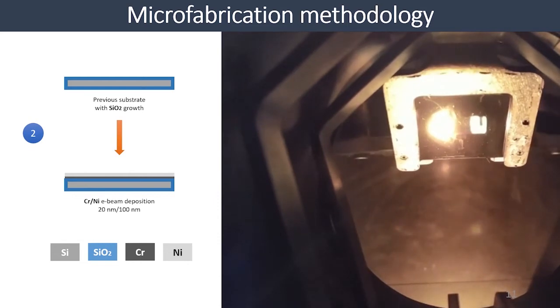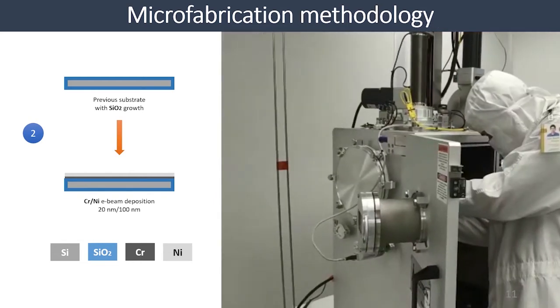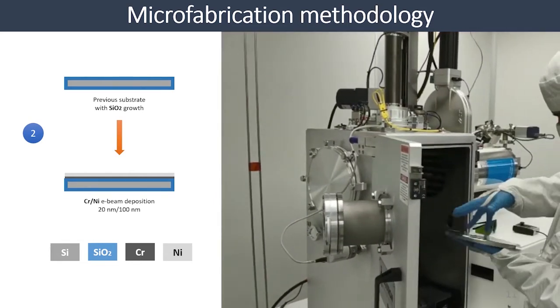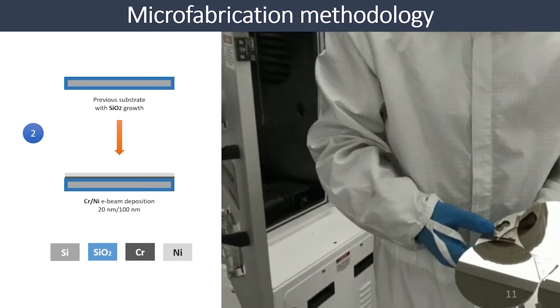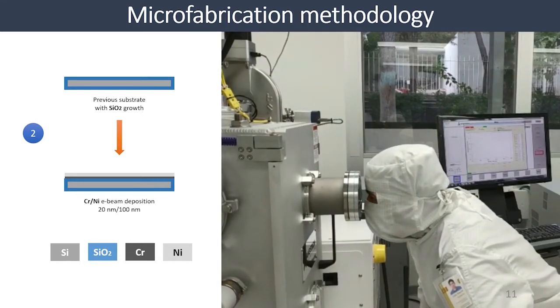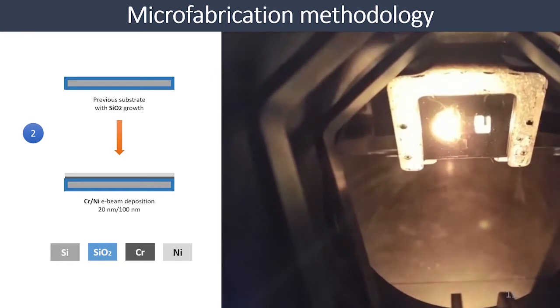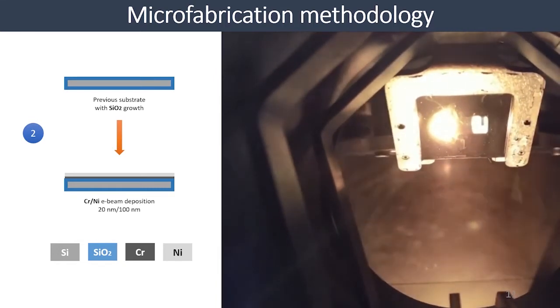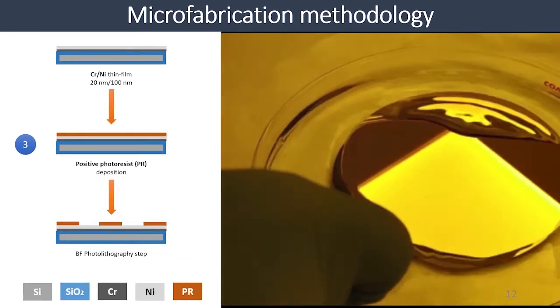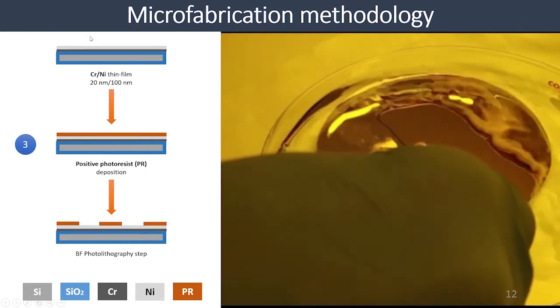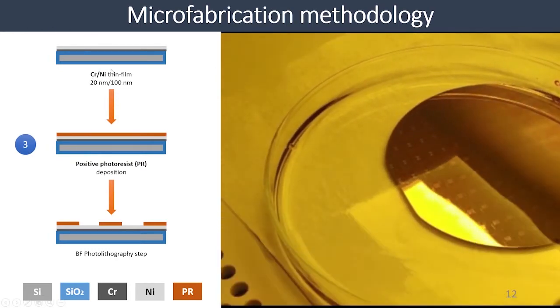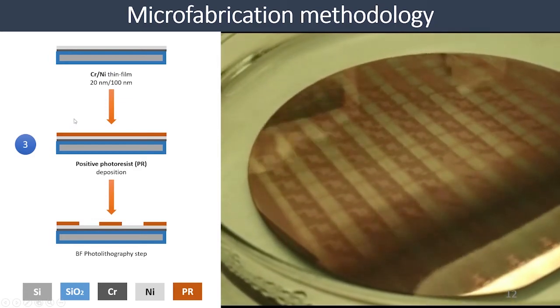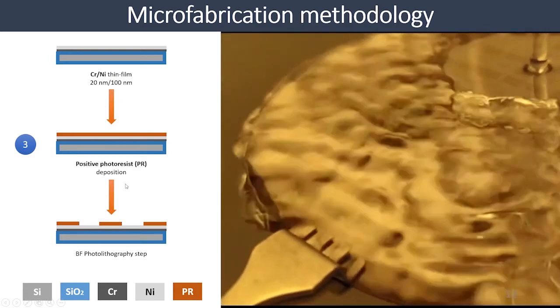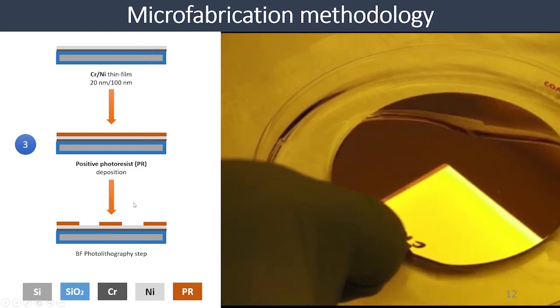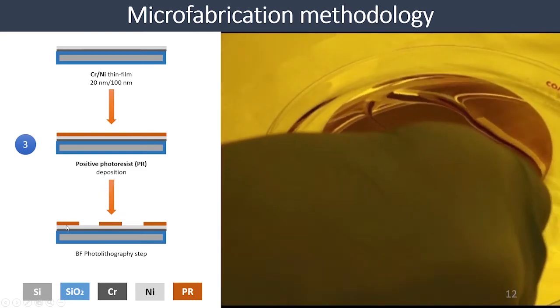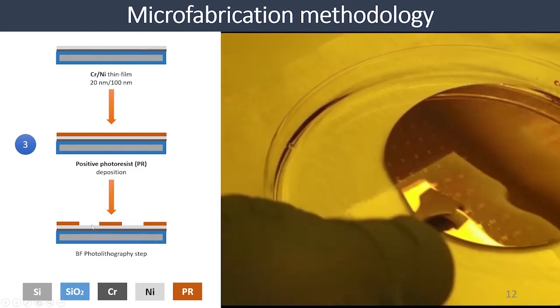This has two consequences. One is that we have more sensors per production day, but we pay for that increase in production with small differences in the metal thickness along the wafers. So there were some resistance differences between each RTD. Then we start with the photolithography process, starting with the chrome nickel thin film. Then we proceed with the positive photoresist deposition and the UV exposure with the bright field photomask, and then the pattern definition with the developer.